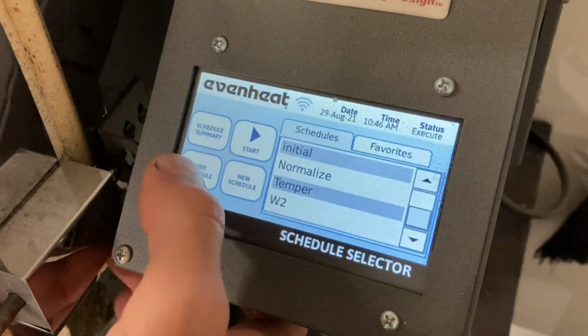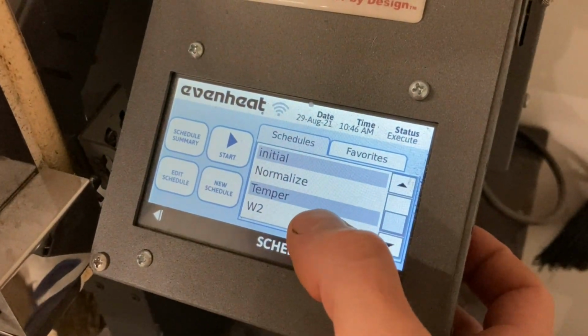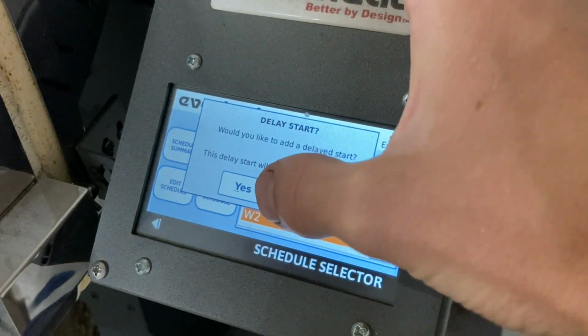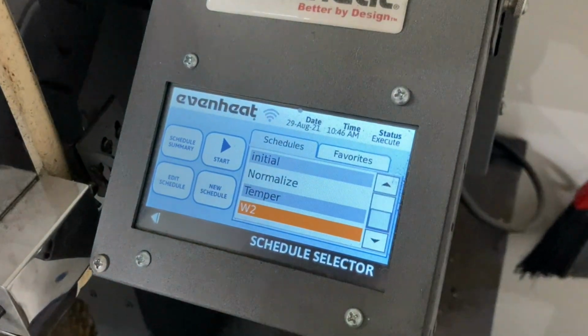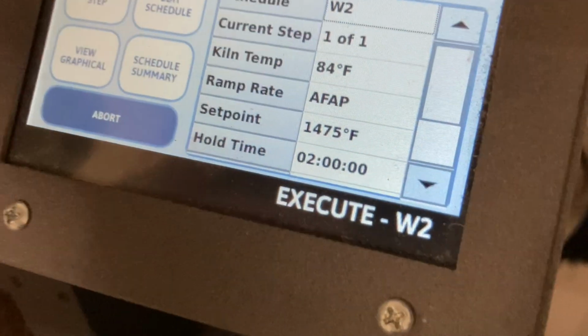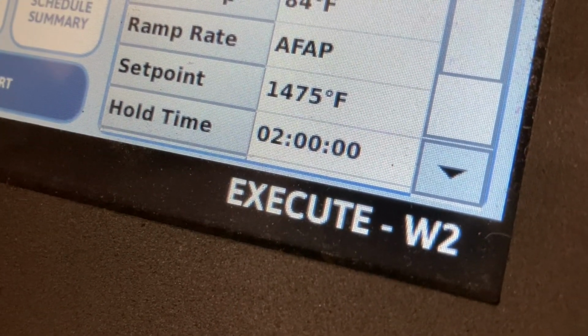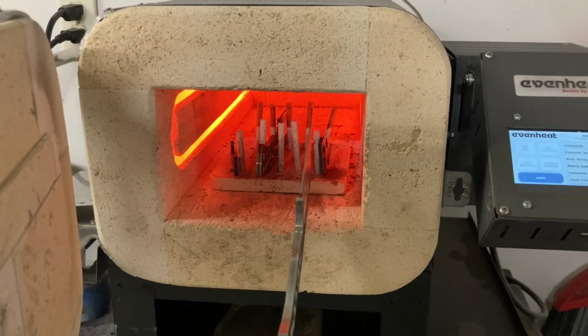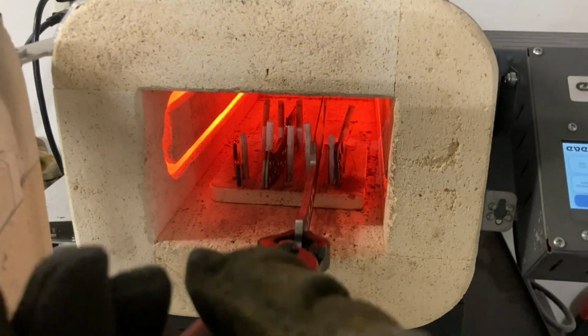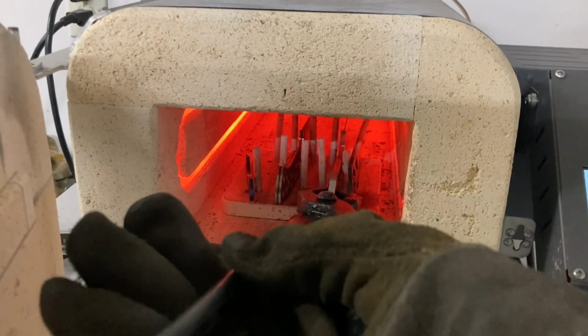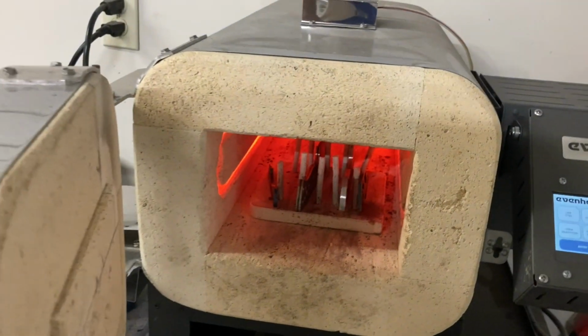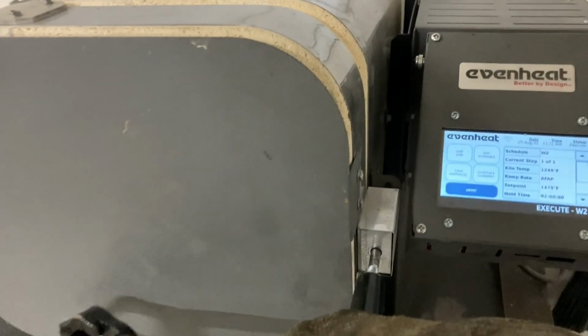Now that it's time to heat treat the knife, I'm going to go ahead and fire up my even heat kiln and turn on my W2 heat treating regimen. That is going to be turning on the oven to around 1475 degrees Fahrenheit. And then once it's up to temperature, I put the knife in, let it come back up to temperature, and then let the blade soak at that 1475 temperature for around 10 or 15 minutes.